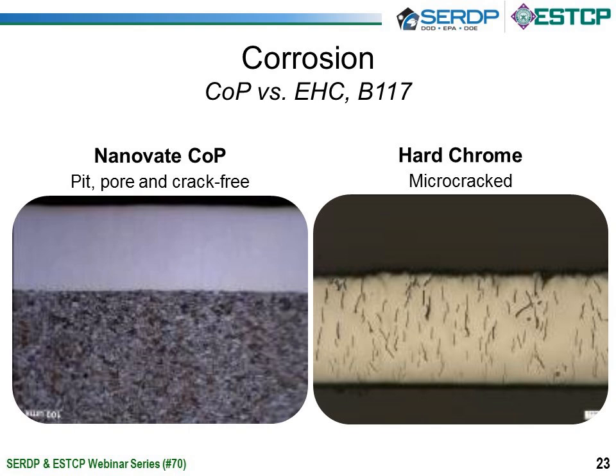And the reason for this performance increase is due to the structure of the coating. This slide shows micrographs of the nano cobalt phos coating compared to that of hard chrome. One of the reasons why hard chrome doesn't do so well in salt spray corrosion is it's microcracked, and these microcracks eventually open up and lead to a pathway where the atmosphere and the environment can penetrate, rusting the substrate, and then that's when you see red rust. With the cobalt phos, it has very good corrosion protection, as there are no cracks. So the substrate is protected, and that's one of the reasons why you see much longer times to red rust.